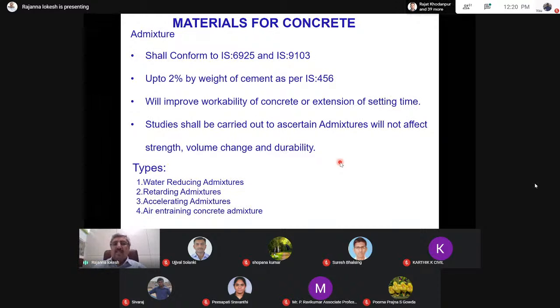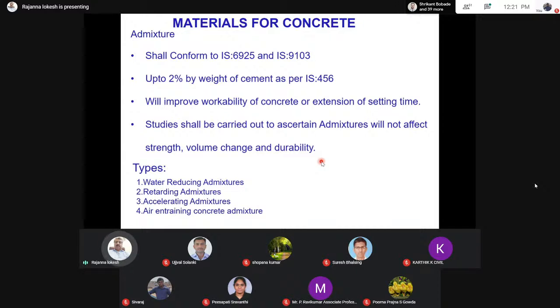So any admixtures that we use should fulfill the requirement of IS 6925 and IS 9103. The maximum percentage of admixtures that can be used is up to 2% by weight of cement. Admixtures will improve the workability of concrete and extend the setting time.